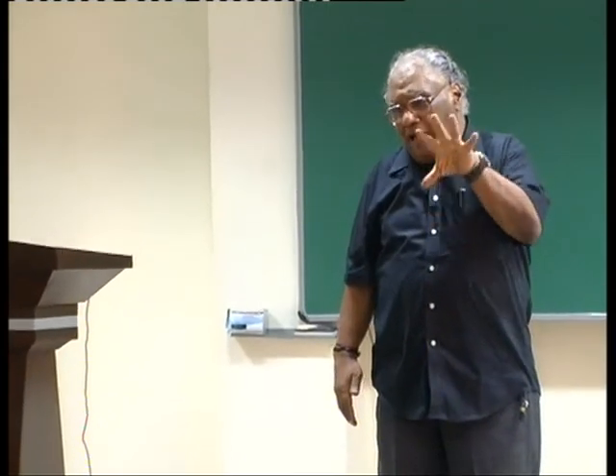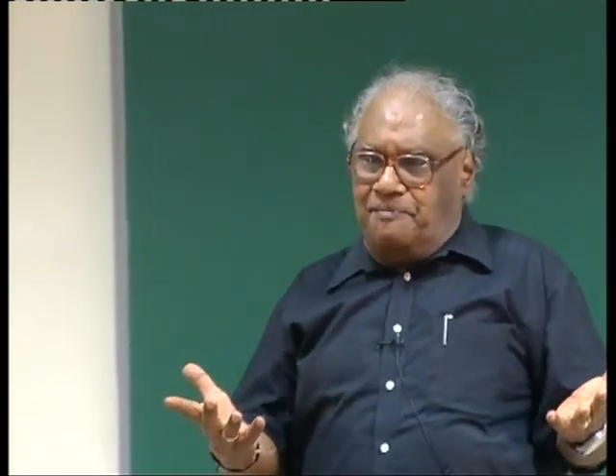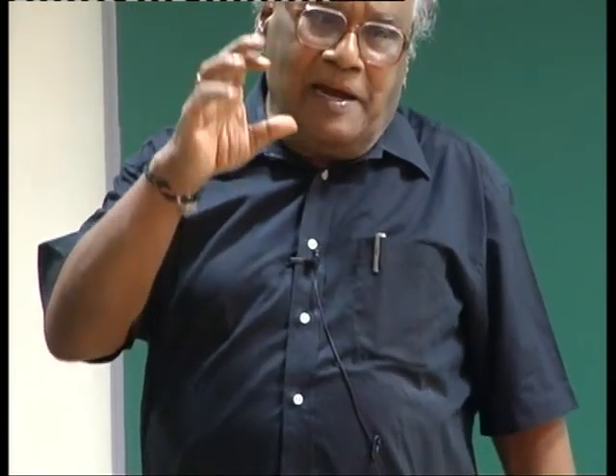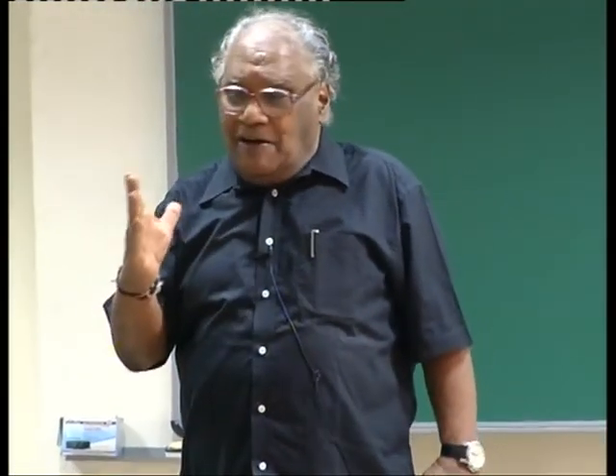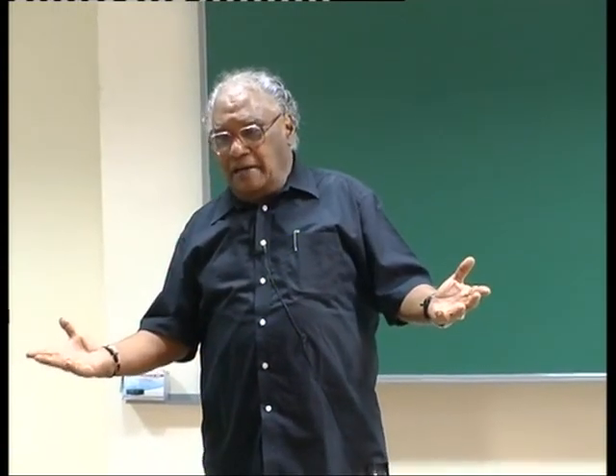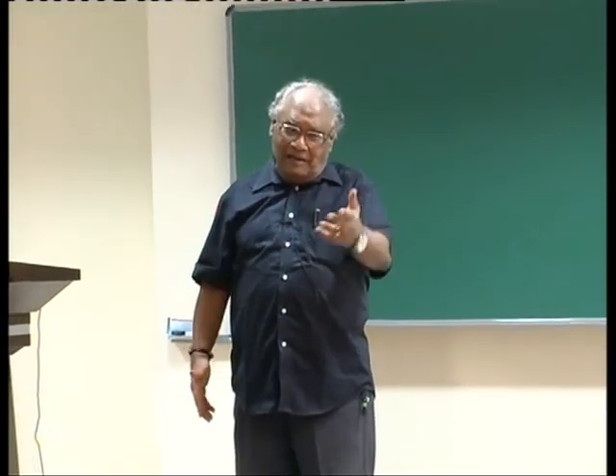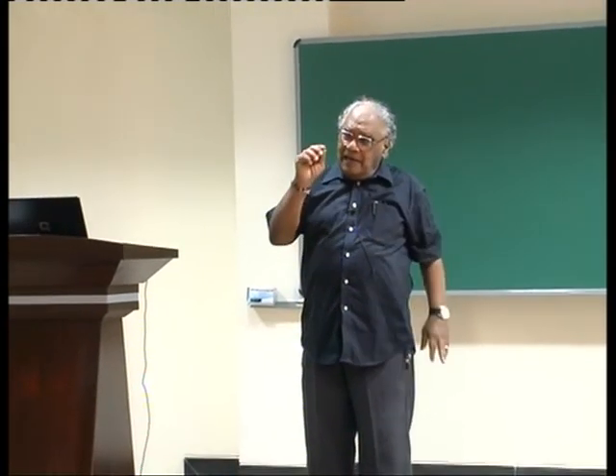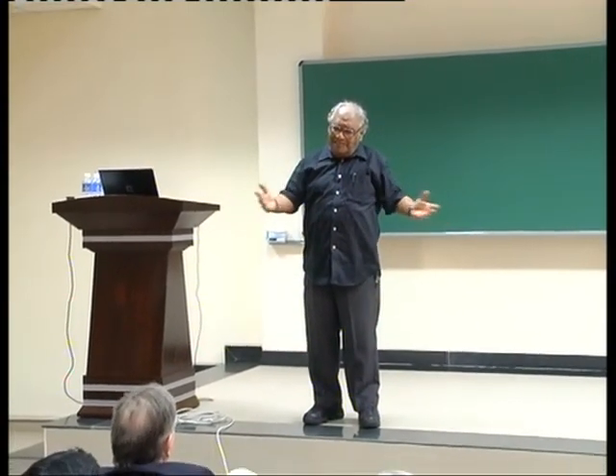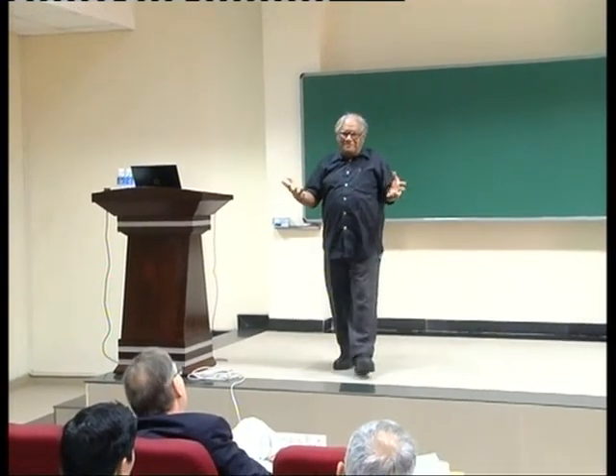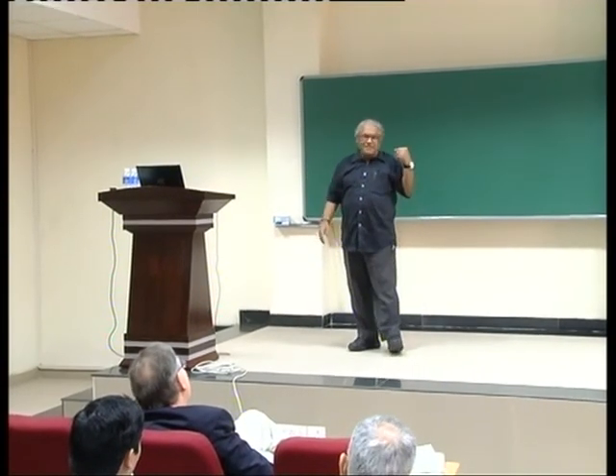It is not cubic, but still a simple enough structure. So the vacancies or defects help you get to a low symmetry structure because of the ordering of these things. That's what Paul Midgley's work has shown. Otherwise, we didn't expect it, but when we made these samples carefully, you can never make exactly a sample. Every sample had different stoichiometry, and they had different structure, different properties. And thanks to Paul Midgley's work, definitely these cation orderings change. It's very well known in oxide chemistry, getting low symmetry structures because of the defect ordering, and that is happening here also.